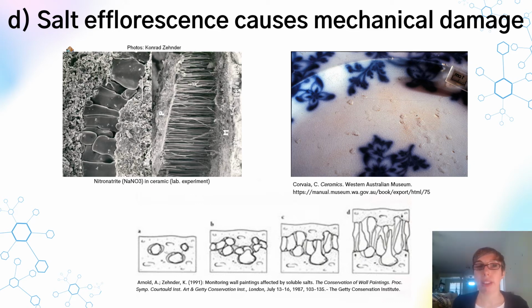As a result, you get all kinds of physical damage like cracking and delamination and other types of mechanical damage that results in basically material loss as the crystal grows and expands in volume. This growth is bad enough, but as we've already discussed, soluble salts have a tendency to deliquesce in high humidity environments and then effloresce and reform when the humidity drops.